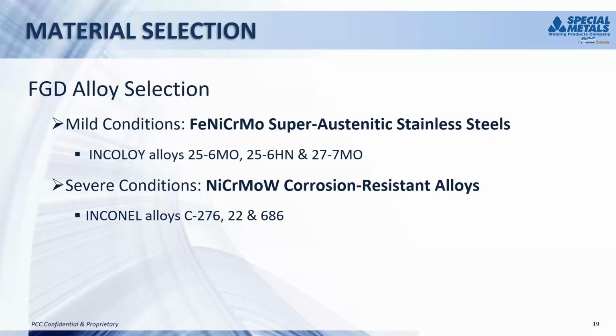While it's only slightly more highly alloyed than the existing products, the corrosion resistance actually approaches that of alloy C276. Yet the cost of the material is only about 60% of that. So here's a case: if you can use these products, their cost is considerably lower than a higher nickel alloy.